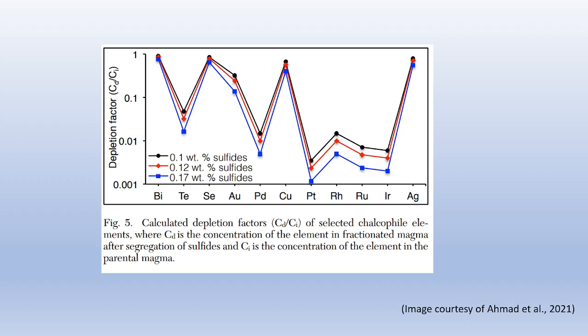Now look at the silver and bismuth. They stand out because they don't follow copper as closely as you might expect. Instead, they remain relatively mobile, hinting at different partitioning behavior in deep crustal conditions compared to shallow systems. And here's the takeaway. All of these effects, the loss of nearly all the PGEs, most of the gold, and part of the copper budget, are caused by less than 0.2% sulfide melt. You wouldn't even notice that amount in a hand sample, but chemically it's devastating.